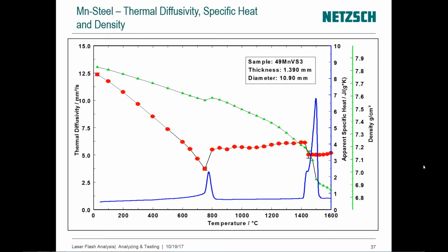and you actually get 3 values of diffusivity, the first approach would be to probably consider the average. But one can think that actually the first diffusivity, if the sample was not stable, the first value is probably important, as is also the last value at that fixed temperature, simply because it shows how the sample is changing, even when you keep the temperature constant. So this is a particular type of application that one must be careful about.